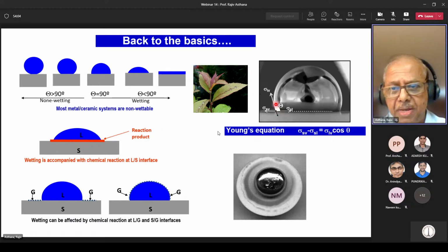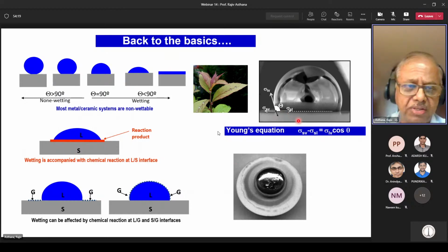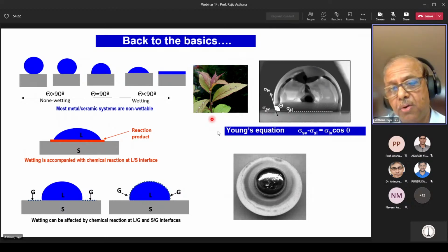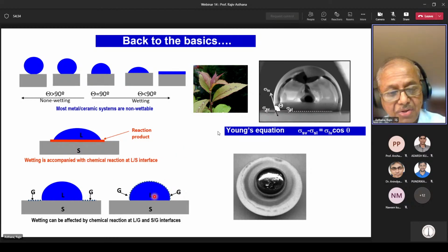So the angle of contact is basically defined as this angle between these different interfacial tensions that occur at surfaces or interfaces between different phases: liquid, vapor, and gas; liquid, vapor, and solid. So all of this formalism was developed more than 100 years ago for low temperature systems, and the same concepts are being used for high temperature systems, although not very effectively because of these unique challenges: reactions, oxidation, surface roughening ahead of the spreading droplet, evaporation and condensation of the liquid ahead of the droplet in the vacuum chamber. So the surface gets modified while the droplet is spreading.